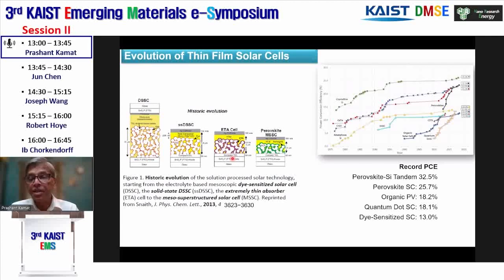Okay, now coming back to solar cells, especially thin film solar cells. In the 90s, we started with the dye-sensitized solar cell, which was about 10 microns thick and involved an electrolyte. From that, we moved on to solid-state DSSC, and then the extremely thin absorber cell, or the semiconductor quantum dot solar cells. And from there, we moved to perovskite solar cells. It's essentially a similar architecture that involves a mesoscopic oxide film covered by a light-absorbing material. In this perovskite, we have these metal halide perovskites, and then we have a hole transport layer and an electron transport layer that drive the charge carriers in opposite directions. And we have gained efficiencies significantly.